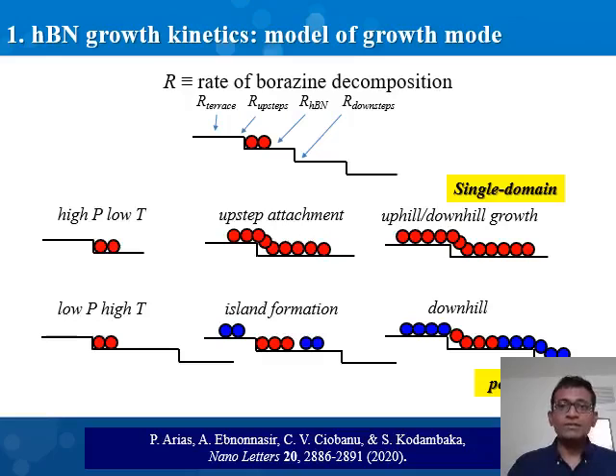So we think the deposition at the down steps is the predominant factor, followed by the attachment at the existing hexagonal boron nitride steps, followed by nearly similar rates of deposition at the terraces and at the up steps. So based on these rates, we expect that when we introduce high borazine flux and lower temperature, there is deposition of hexagonal boron nitride occurring at the down steps, and these already deposited domains continue to grow both along the down terrace and across the up terrace, leading to a single domain formation along both the terraces. And this is what has been referred to in the community as the carpet-like growth.